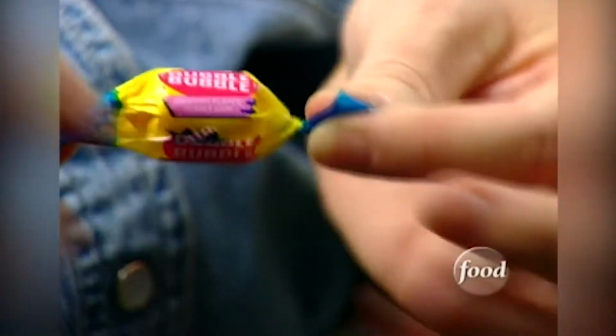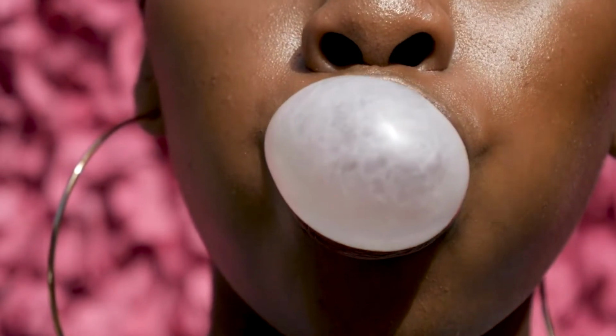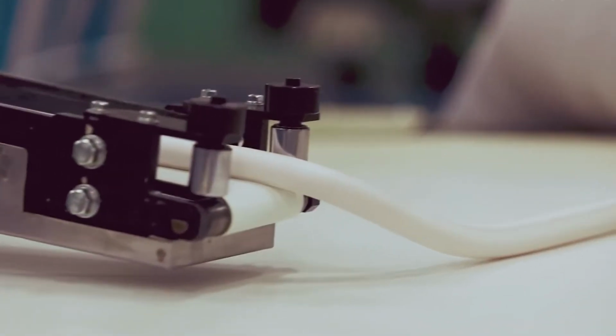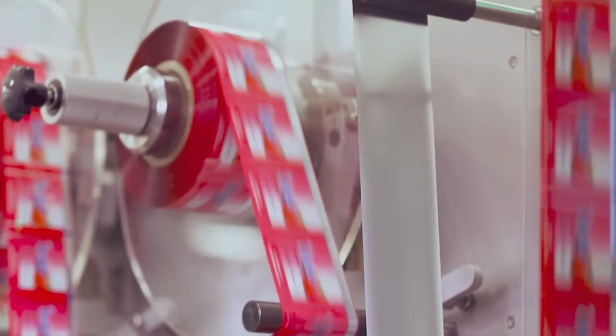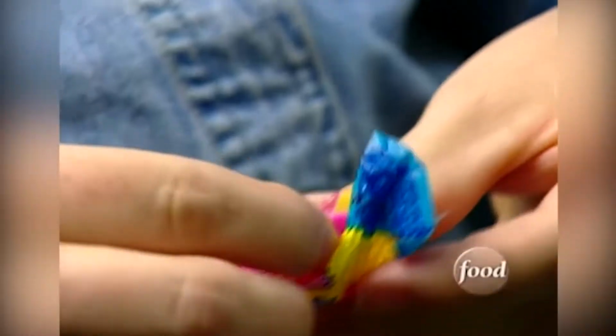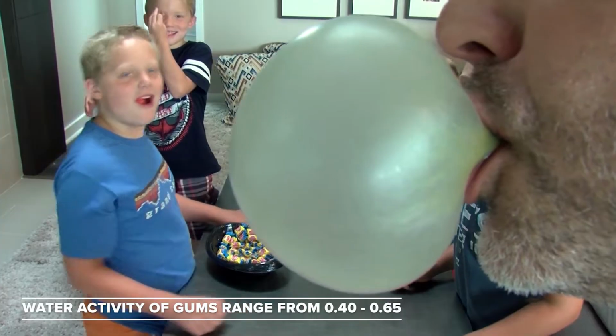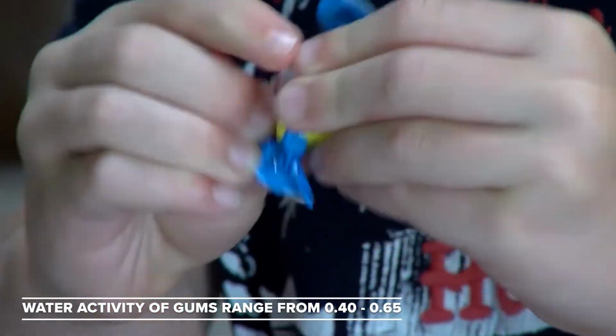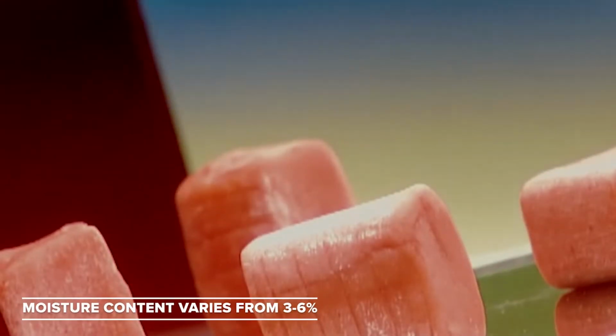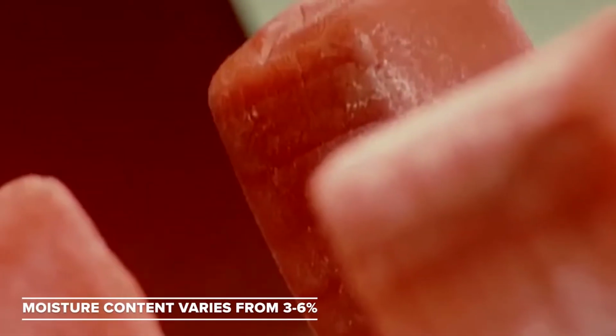Cube-shaped or chunky gum, usually intended for blowing bubbles, is called cut and wrapped gum because it's usually separated from the strand of gum being extruded and wrapped directly. Chewing gum is quite stable in storage due to its unreactive nature and low moisture content. The water activity of the gum ranges from 0.40 to 0.65. The moisture content of the gum varies between 3 and 6%.